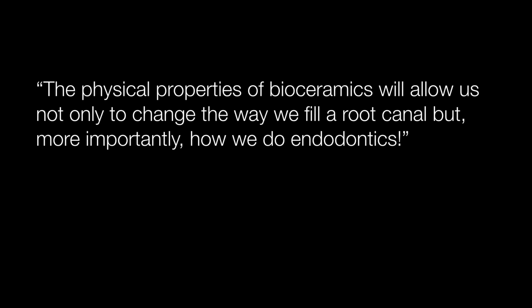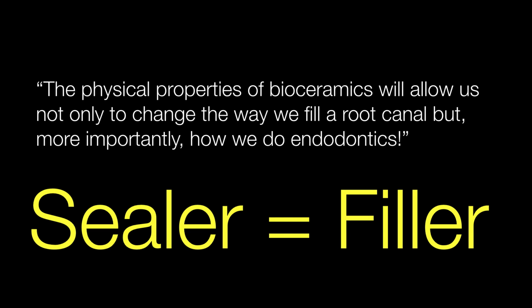So as a result of all these improvements in the material properties of the sealer, all of a sudden the game has changed, and we don't have the limitations of the old types of sealers. So suddenly, as a result of these material improvements, we're not only just changing the way we fill a root canal, but more importantly, the way we do endodontics, because for the first time in our history, our sealer is actually a filler. So when it comes to comparing now fillers, you would say gutta-percha is a filler too.